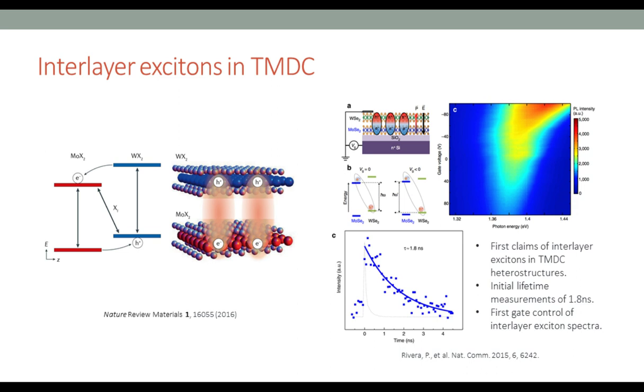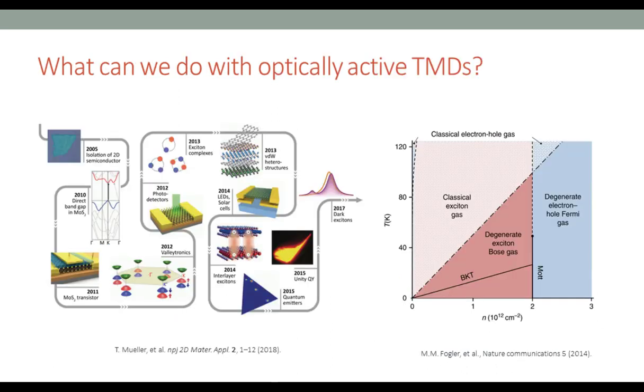The first claims of interlayer excitons were in 2015. They showed that there is a gate dependence in the luminescence energy, and the lifetime for the recombination is also much longer, around 1.8 nanoseconds, so 3 orders of magnitude longer than the monolayer limit. For a broader perspective, here's the history that I mentioned before. Around 2005 is when they first isolated the semiconductor, and then they discovered that it's a direct band gap. Then they made all sorts of very cool applications, such as transistors, photodetectors, and valleytronics. And now we're trying to do similar kinds of applications with interlayer excitons.